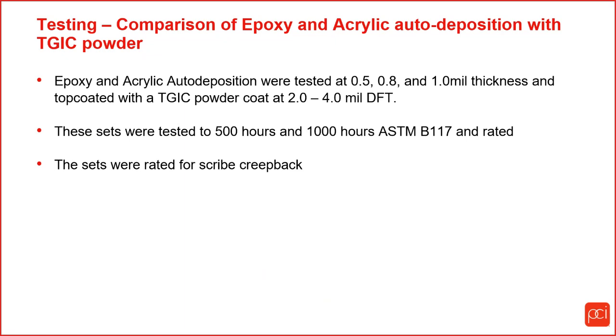Dry film thickness. We coated these with a Spraymation machine for consistency. They were all painted at the same time and coated to where it wasn't some at 2 and some at 4. And then these panels were tested to 500 and 1,000 hour salt spray, ASTM B117, and then they were rated for scribe creep back.